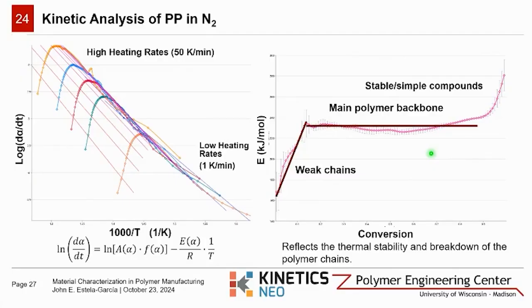Following this, we observe a region of relatively constant activation energy. This represents a systematic unzipping of the polymer backbone. So this is what we refer to as that main chain scission. This stage involves the breakdown of the primary polymer chains.